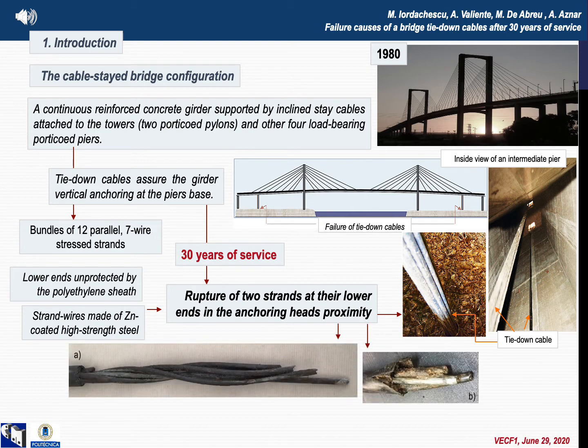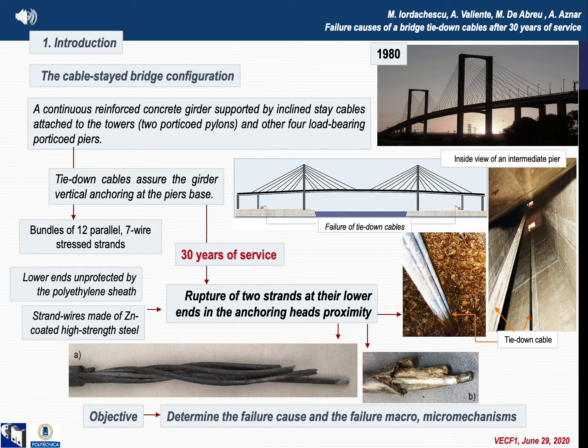The samples supplied for the analysis of the service failure and pertinent laboratory tests were strand sections, polyethylene sheeted, of 3 meters length, having at one of the ends the illustrated rupture details. Close to the fracture zone, at naked eye can be observed that some of the fractured wires still retain part of their original zinc-coated protection.